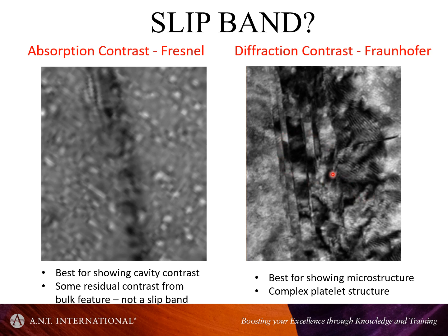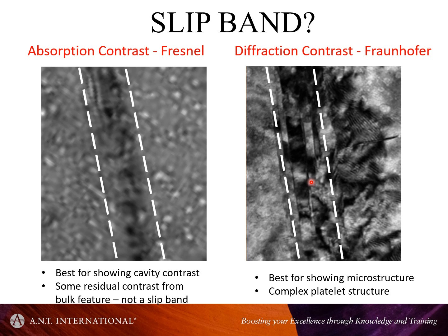And this is the structure that was there. It was identified as a cluster, an accumulation, an agglomeration of microtwins. So this vague thing here along which the cracking was observed is actually a cluster of microtwins. So it begs the question, well, it's not a slip band, and this is microtwins. So in one year they're reporting this, and then the next time they're reporting on it, it's a set of microtwins. So I'm not sure what the conclusions would be from the group that did this work now.